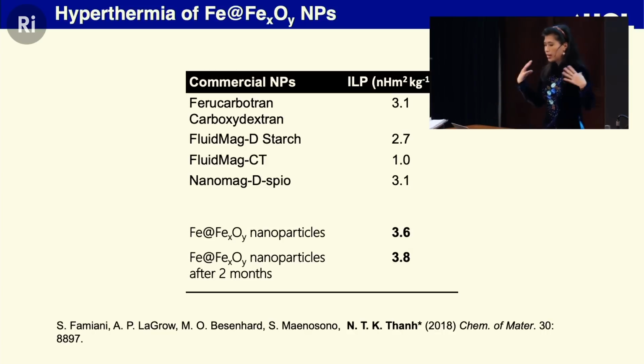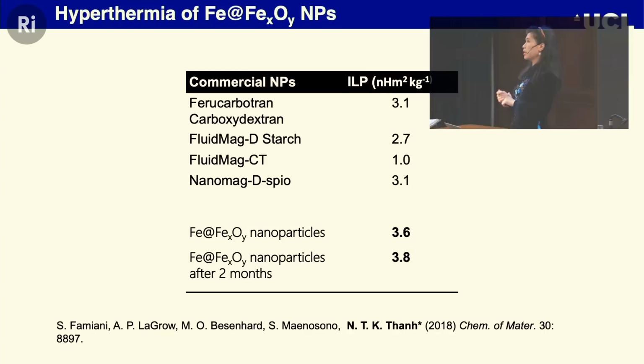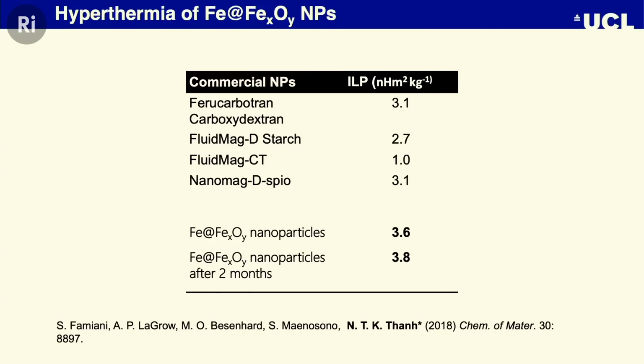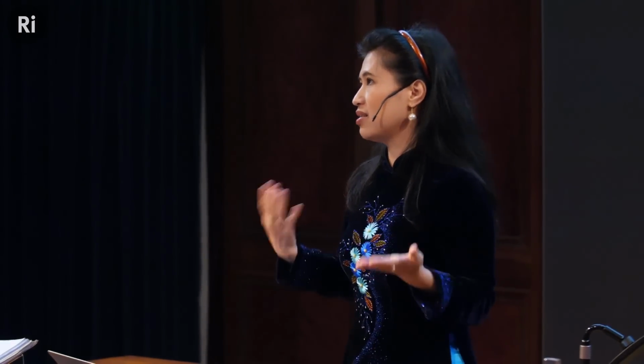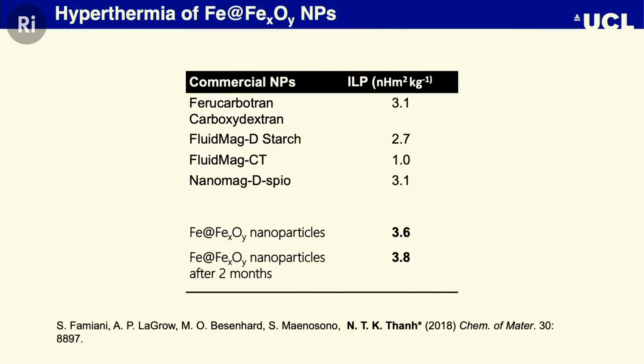And then one other parameter, which was derived by Professor Quentin Pankhurst, is this ILP. It's the intrinsic loss power. Because when you use a higher field and higher frequency, you will have higher heating. So you obviously want to report that you have really high heating, but you used very high field and high frequency. So Quentin makes people report honestly by standardizing it, dividing by H squared and the frequency, so you standardize with field and frequency. What you are left with is an intrinsic loss power, data that we can compare between different systems.